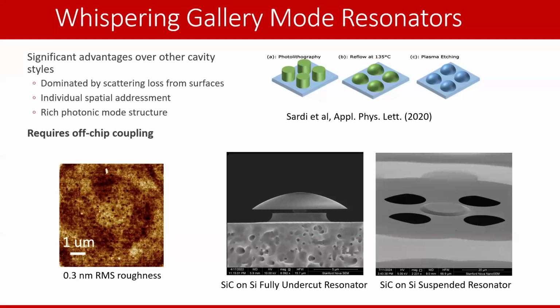We thought a little bit about doing some pillar underneath, or some electrical contacts prior to bonding and then bonding afterwards. But really, this is the most straightforward. And the undercut is actually not that bad, because it's oxide on silicon, so you can do HF vapor for the oxide layer, and then xenon difluoride for the silicon layer, and it's completely fine. I will say that we use HSQ for that oxide layer, and so the HF vapor goes through it like a hot knife through butter.